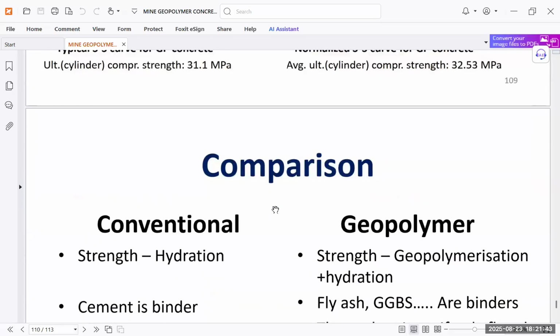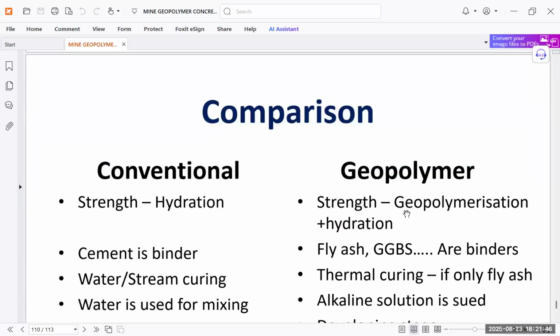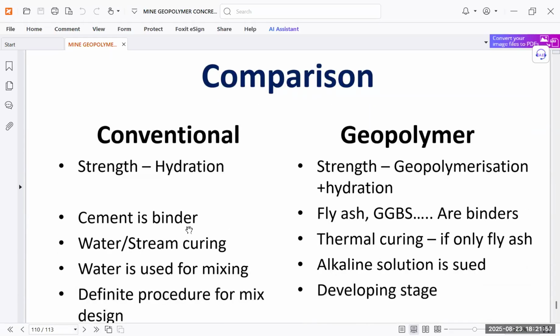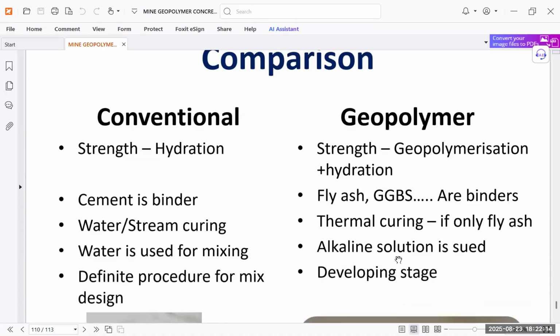So in the end, we can compare this. The conventional concrete is this, geopolymer concrete is this. In conventional concrete, strength comes from hydration, but in geopolymer, strength comes from geopolymerization plus hydration. Cement is the binder in normal concrete, and for geopolymer, fly ash and GGBS are the binders. Only fly ash is there in this case. Water is used for mixing in conventional concrete, and an alkaline solution is used in geopolymer concrete.